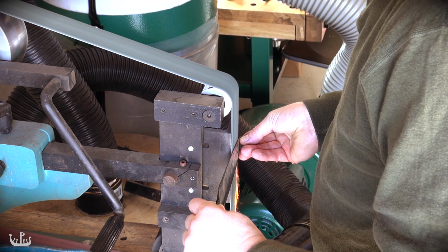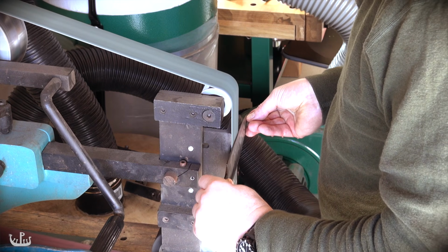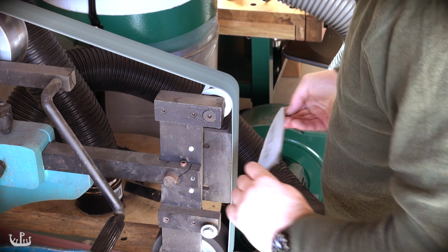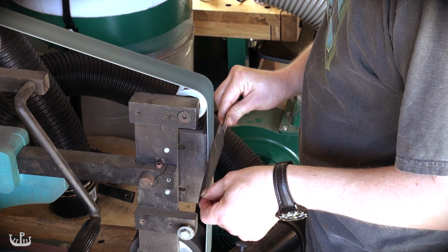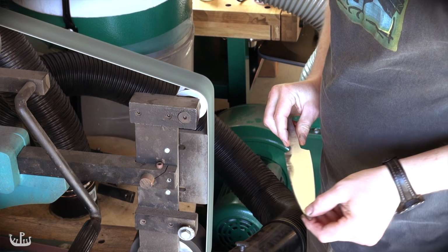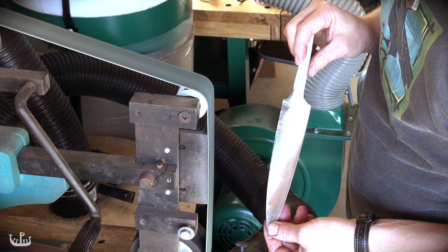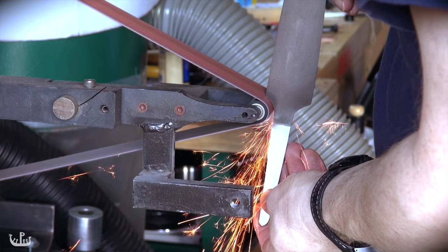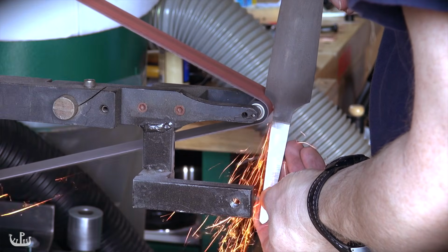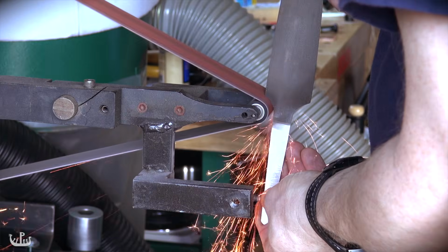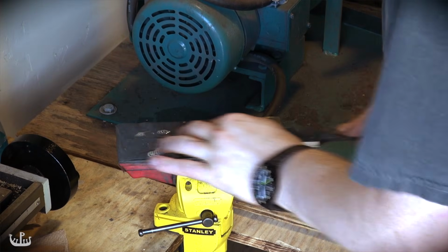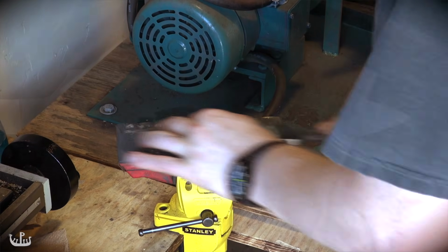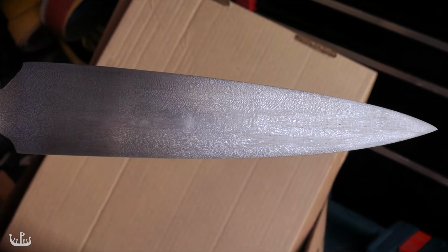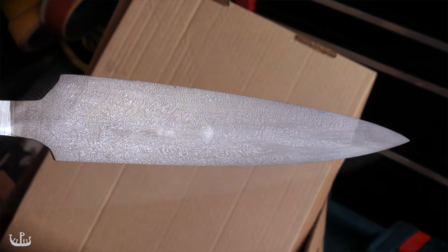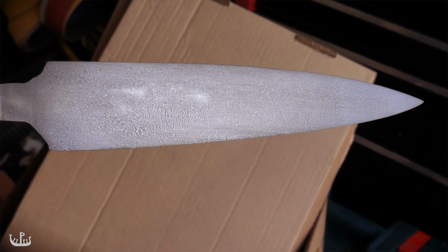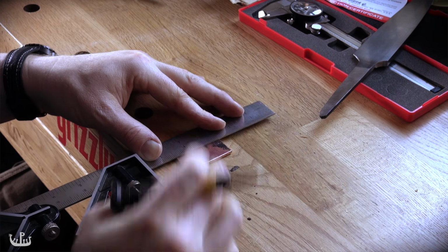Now comes another time-consuming step in which the blade is further thinned using finer grit belts. This is also the time where the profile is cleaned up to make it easier to fit a bolster and handle. Once almost all the grinder marks have been removed, it is time for a quick test edge to see the patterning of the steel. The pattern that we see here is essentially dendritic and not as refined as one would expect from traditional Wootz steel. That is disappointing, but just a step on the way to perfection.